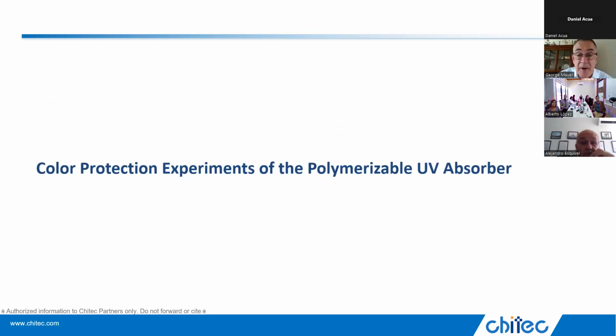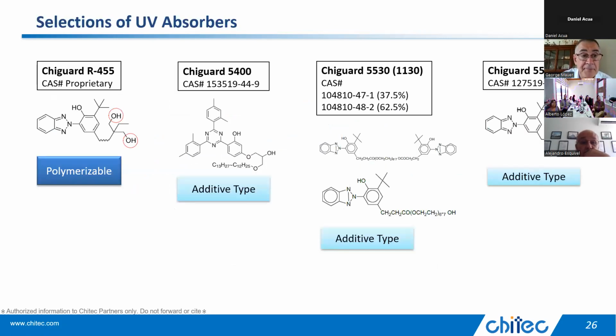Okay, we did some experiments here, which are kind of interesting with color. We want to compare some of these materials. There's some interesting considerations. The R455 is a benzotriazole. As I said, that has the broad spectrum. The Chi-Guard 5400, it doesn't migrate very much either. And it's got that hydroxyl that can react once. It's secondary, so it's not quite as efficient. This polymerizes in, where this can graft in a little bit.